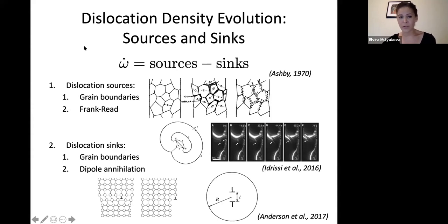So for the particular model we chose, which is also common in a lot of other modeling approaches to model this evolution, we'll look mainly at two dislocation sources that are thought to be dominant for Earth-like conditions and also in olivine. One of them is grain boundaries, exemplified here in the work by Ashby from 1970. Grains in a polycrystalline material are polygons, so when they try to move relative to each other, in order to avoid opening any gaps or voids or overlapping, in other words to be strain compatible, one of the ways they can do so is by introducing dislocations along the grain boundaries. These are termed the geometrically necessary dislocations. So this is one potential source, close to the grain boundaries, for increasing the dislocation density.